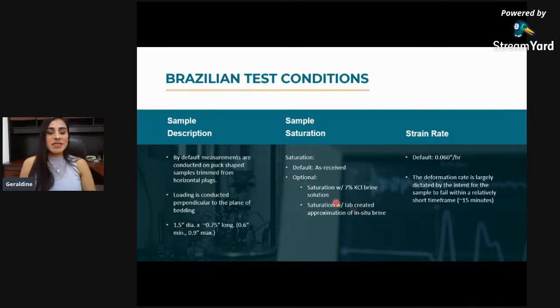Okay, then another test is the Brazilian test, and the conditions for this test are by default or standard. You want puck-shaped samples, like a disc of sample or a cookie of sample, trimmed from horizontal plugs. That means that you have a horizontal plug that was sampled from the core in a horizontally oriented direction, and from that plug you trim a disc, and this will be loaded in a plane perpendicular to the bedding. I will show you in the next slide a picture of that.